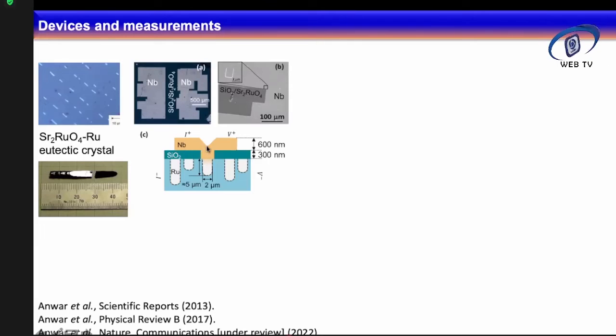At the top of that, I deposited another superconductor, which is a normal superconductor, niobium. So now this is a device between a normal superconductor and a chiral superconductor, a superconductor that breaks time reverse symmetry. Now this is also a Josephson junction.